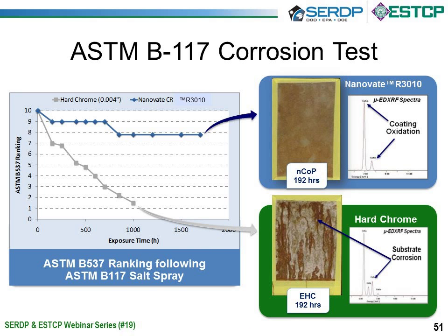In terms of properties, corrosion testing was one of the original tests that we performed, and as John mentioned earlier, there is indeed noticeable improvement between corrosion performance of a cobalt phosphorus electroplated steel alloy and hard chrome plated. It's predominantly due to the micro cracking that occurs in hard chrome plating, and in the lower photograph, that's readily observable. How you have defects in the electroplate that are a natural occurrence in chrome plating that result in substrate corrosion.